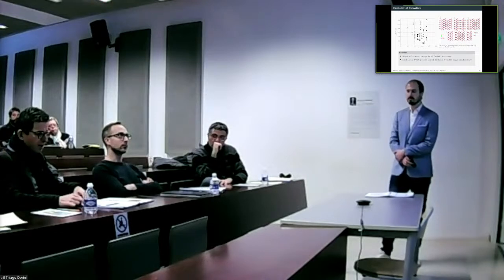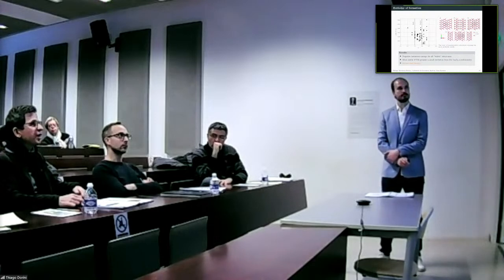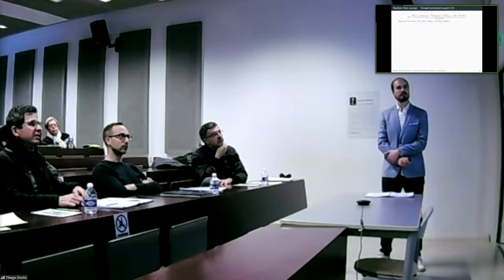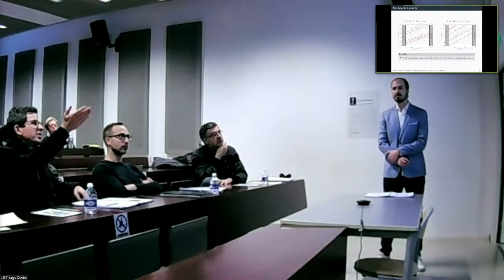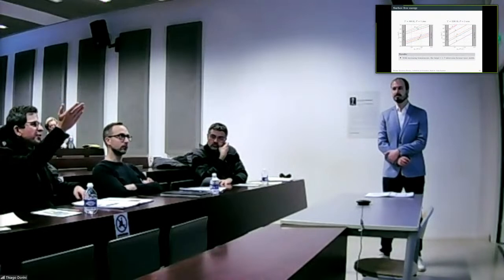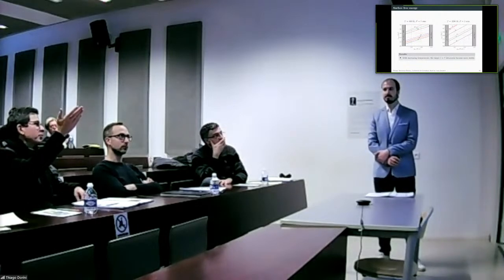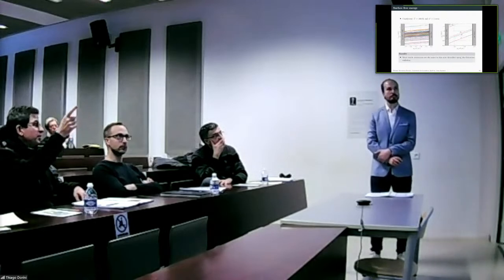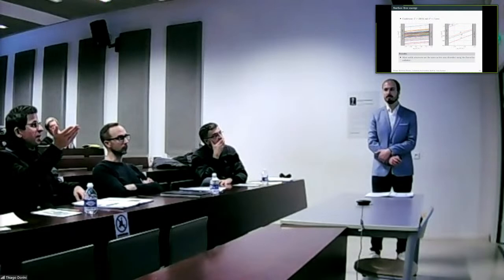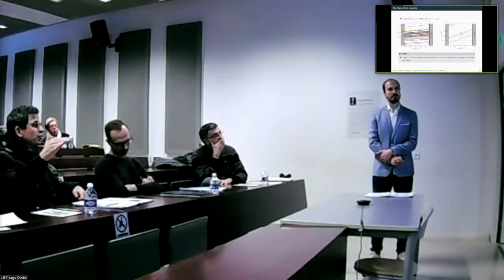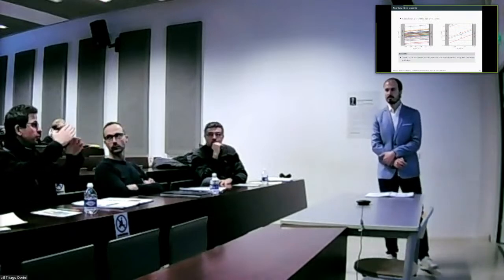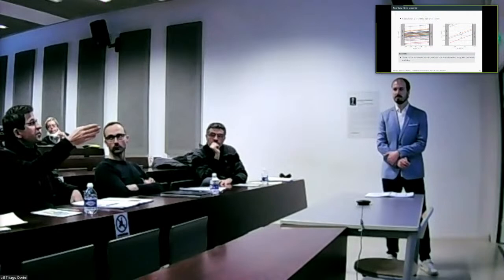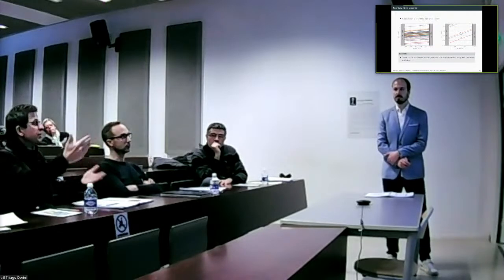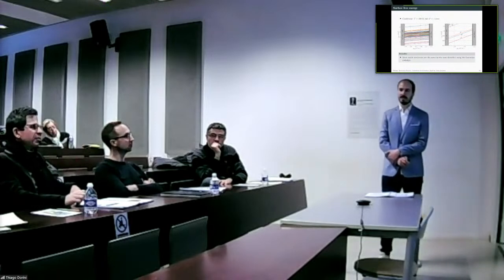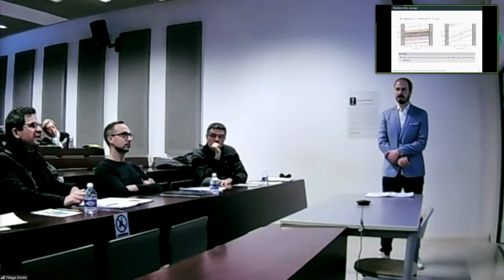Now, I like very much your summary of this chapter in this correlation. Yeah, well, just as a technical point, very clearly the relative stability of structures does not change as a function of indium chemical potential. So these plots are in fact not so very interesting. Whereas it changes radically as a function of oxygen chemical potential. So plotting the same thing as a function of oxygen chemical potential would show you a lot of crossings that would be very pertinent to identify the experimental conditions under which these changes could take place. It's true. Yes. Just another way of expressing the same results.